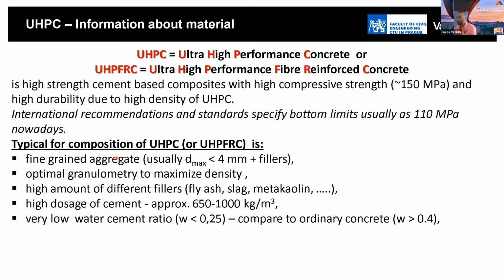We also use a very low water cement ratio. That is because if we increase the volume of the cement in the concrete mass, we can reduce the water cement ratio. The typical water cement ratio is less than 0.25. Compared to ordinary, normal concrete, for example grade C30/37, we use a water cement ratio of more than 0.4. That means that from the chemical point of view, we don't have enough water for cement hydration.